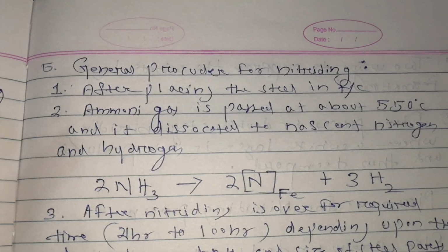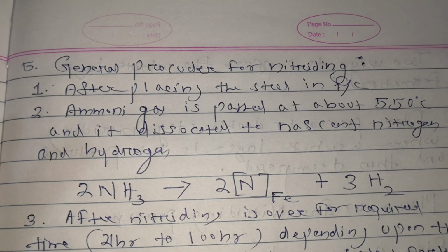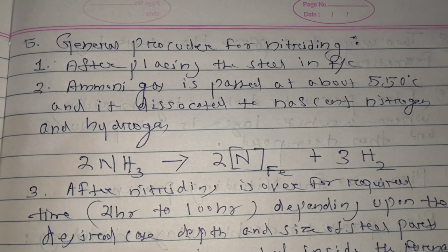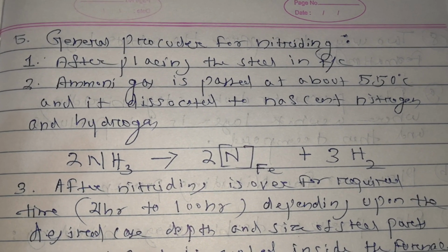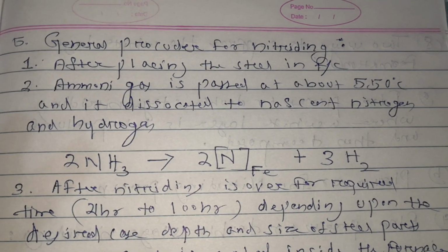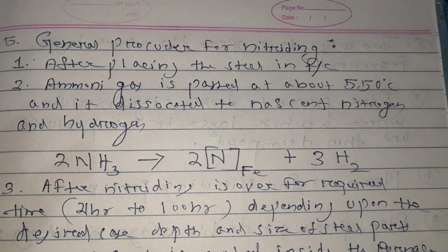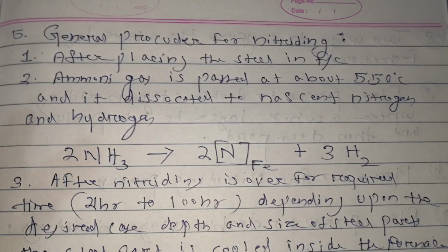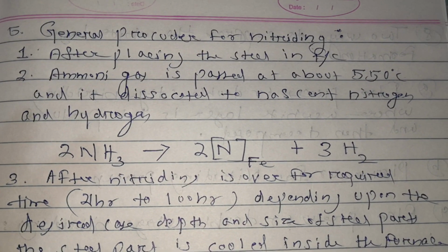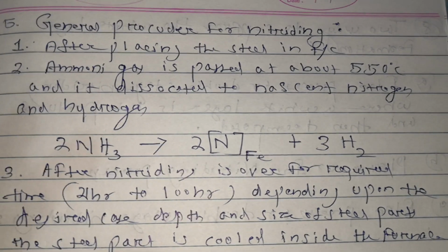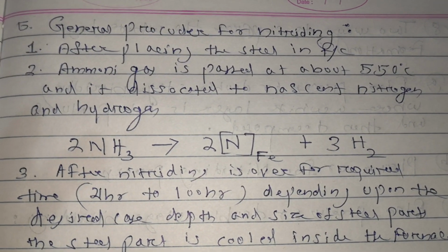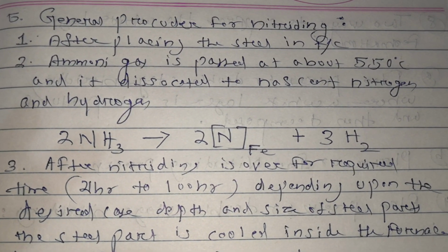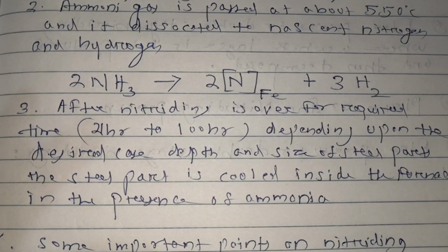Then the general procedure for nitriding heat treatment. So first the steel specimen is placed inside the furnace and it is heated to a temperature of 550 degrees centigrade. At that temperature ammonia gas is passed into the furnace, and this ammonia gas dissociates into nascent nitrogen and hydrogen. You can see this reaction.